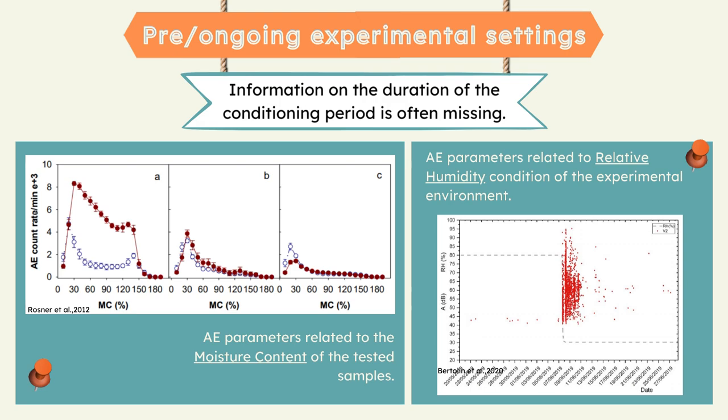Sometimes, the acoustic emission parameters are also related to the relative humidity condition of the environment in which the tests take place. The plot shown on the right of this slide is reported as an example of this kind of investigation carried out by Bertolin et al. in 2020. Acoustic emission signals here have been recorded during two stages of an experimental procedure in a climate chamber at two different relative humidity levels that are visible through the dashed gray line,